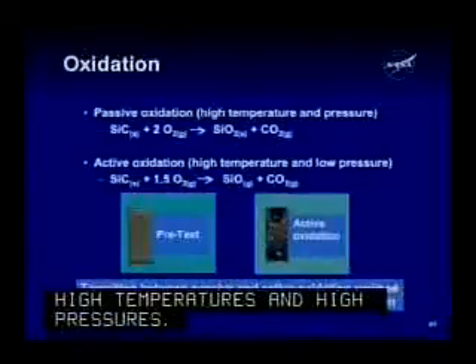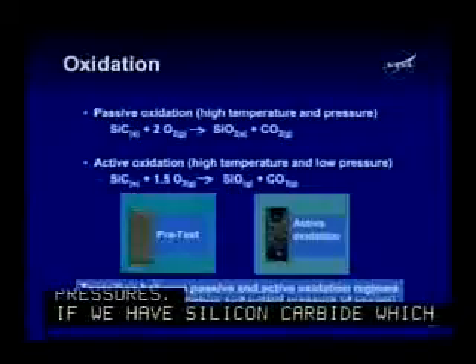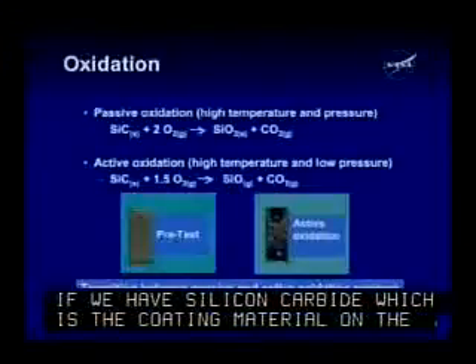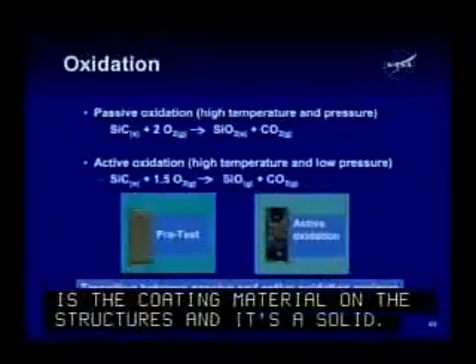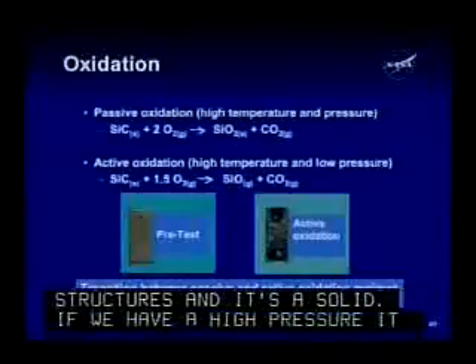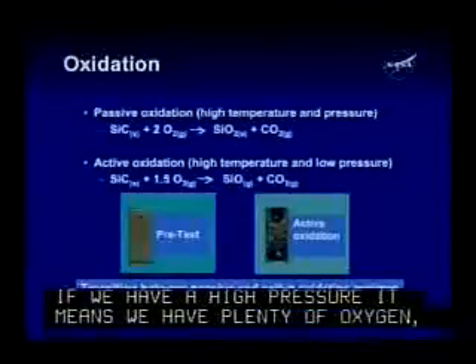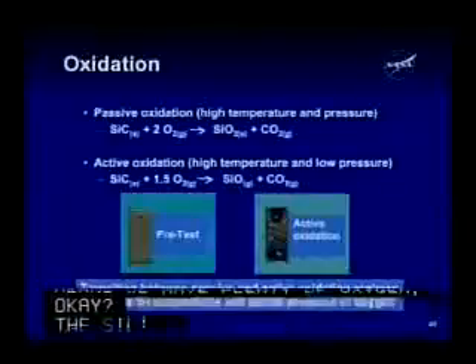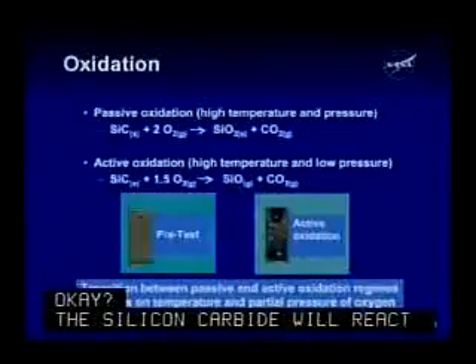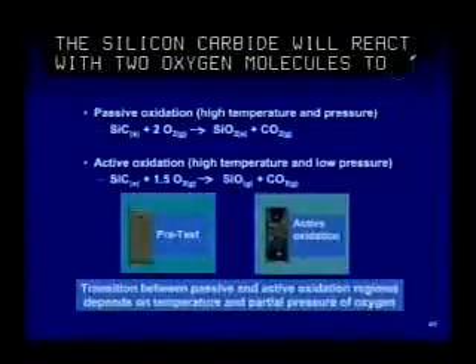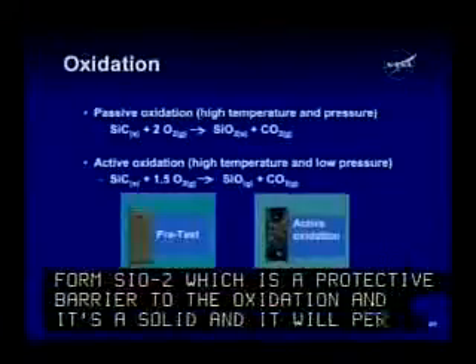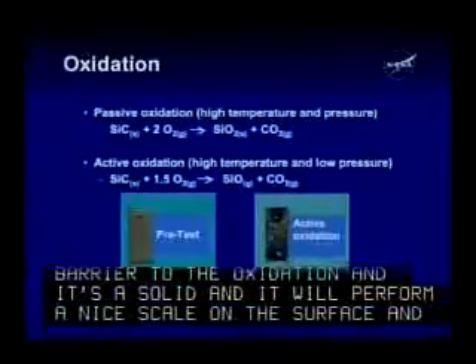Okay, if we look at the little equation there, if we have silicon carbide, which is the coating material on the structures, and it's a solid, and if we have a high pressure, it means we have plenty of oxygen. The silicon carbide is going to react with 2 oxygen molecules to form SiO2, which is a protective barrier to the oxidation. It's a solid. It's going to form a nice scale on the surface. And we have some CO2 gas that's given off.